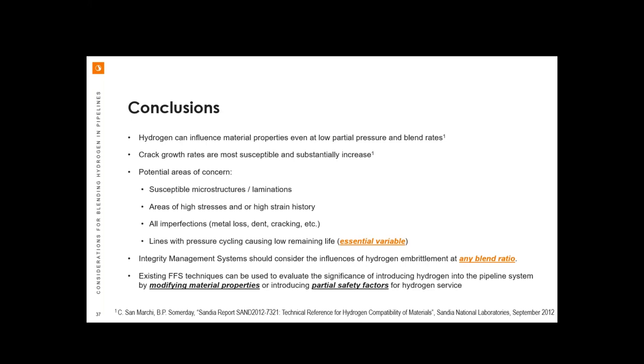So in conclusion, I think Christian and I have presented here today that hydrogen can have a significant influence on the material properties, even at low partial pressure and low blend rates. The crack growth rates appear to be the most susceptible and substantially increase by an order of magnitude. We've gone over some potential areas of concern. Susceptible microstructures, and I hadn't talked about laminations. Laminations can also be a problem, particularly if they're sloping or interacting with other features, surface laps. We are concerned about areas of high stress and strain history, and of course, the existing condition, all types of features that could interact with hydrogen.